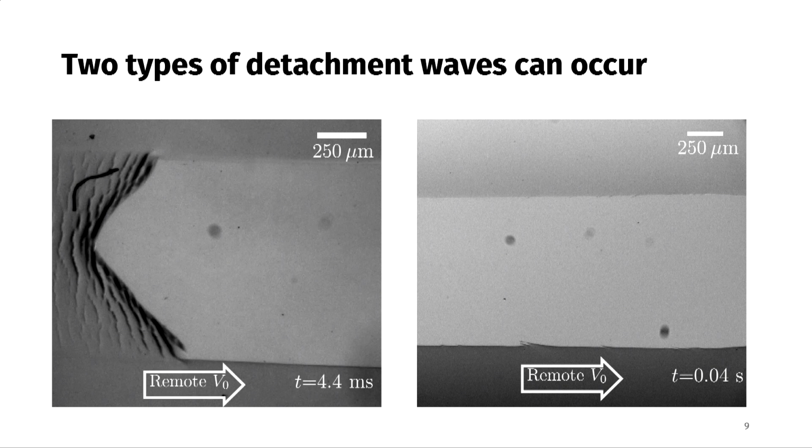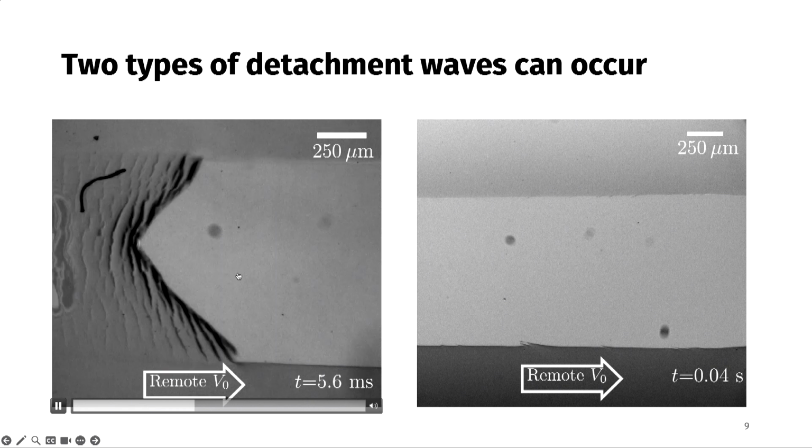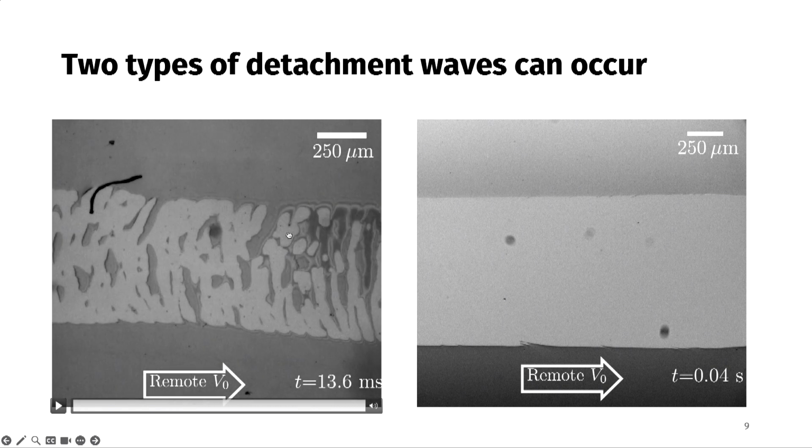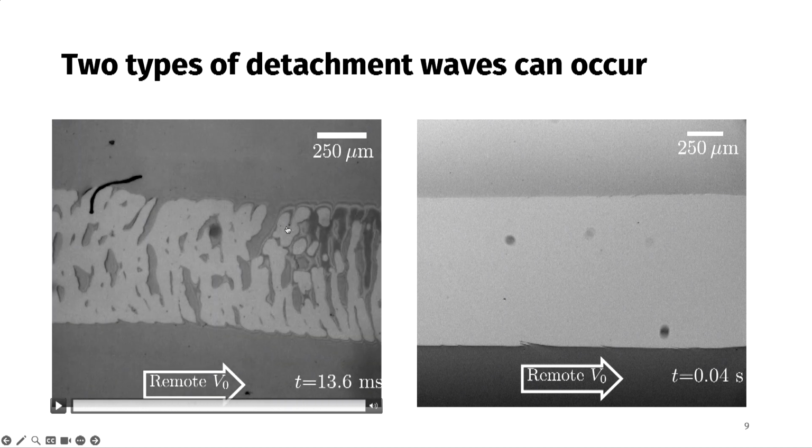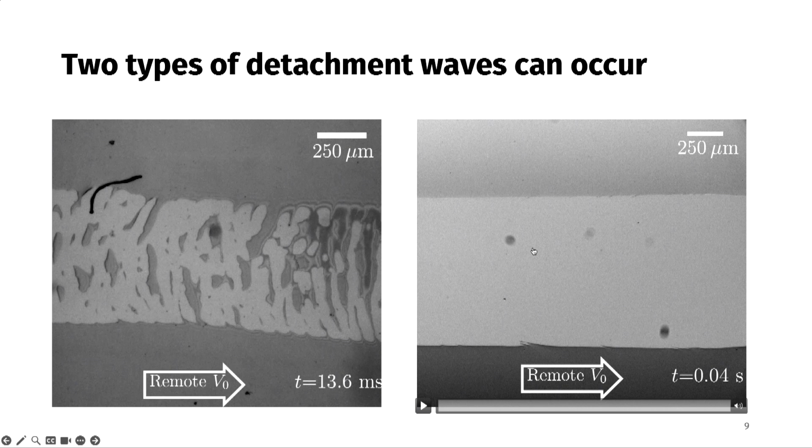If you look at points that are outside the contact, they move at uniform speed. But if you look at this point within the contact, it remains stationary until this detachment zone goes past it. Right? And now it jumps by a certain amount. So the wave comes and it jumps to here. You can see that the interface remains stationary until the wave comes, and then once the wave comes, it jumps. You change the normal load, change the velocities. Again, details of how much it's reduced and so on are second order information right now.